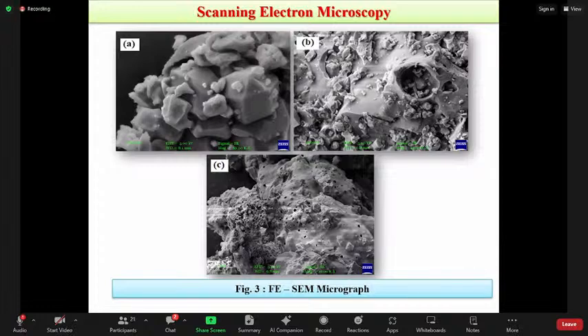In the scanning electron microscopy, all SEM images show a similar porous morphological structure. But the first image is a little more porous than the other 2 images. According to the X-ray diffraction study, the particle size is calculated to be less than 100 nanometer, and it is confirmed by the size in the SEM images. The SEM images show sizes less than 100 nanometer.